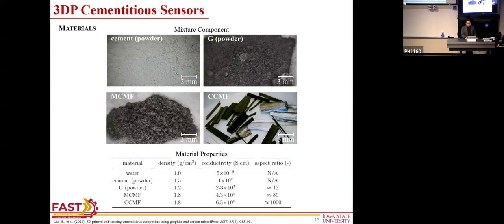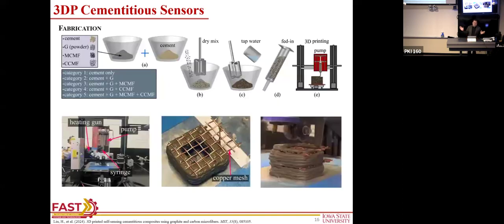I won't get too much into the details. Essentially, this is how we make it. It's like making a cake: all the dry ingredients together, mix it, then we add water, and that makes our slurry. The challenge is to find the right amount of water when you print to make sure that you can 3D print indeed, that you don't have slumping of the material, and also that you have a good interlayer bonding.